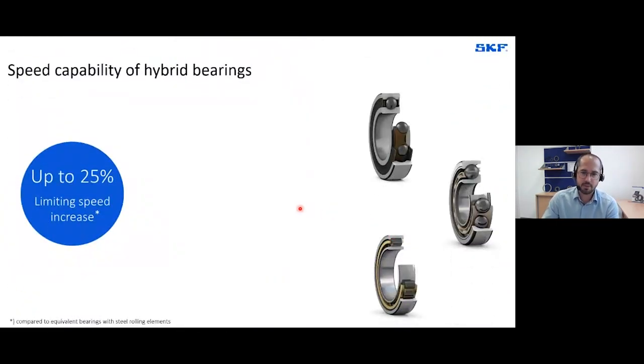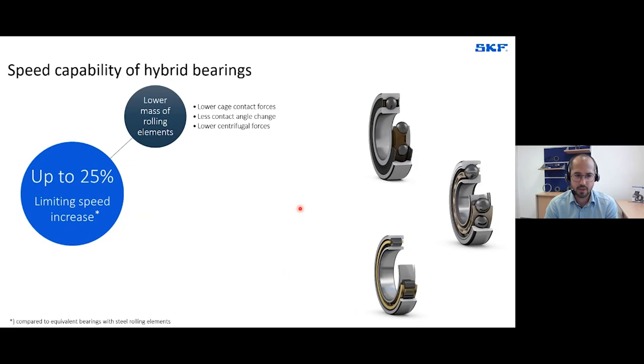Hybrid bearings have a speed capability which is up to 25% higher than the one of equivalent steel bearings. It is given by the lower mass of the rolling elements. Lower mass means we have less internal forces like cage contact forces or centrifugal forces acting on the rings, but we have also improved kinematic behavior inside the bearing. So there is less contact angle change, for example, in hybrid bearings compared to steel bearings.